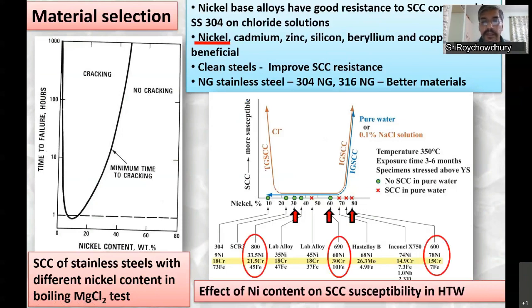Alloy 800, which is the steam generator tube used in our nuclear power plants, lies in the base of this bucket, which indicates it has very low SCC susceptibility. So we have very good experience in our nuclear reactors, no IGSCC occurrences. Similarly, alloy 690 also has very low susceptibility to IGSCC. But alloy 600, which was initially used as steam generator tube material, has very high susceptibility to IGSCC in this high temperature water simulating nuclear environment.